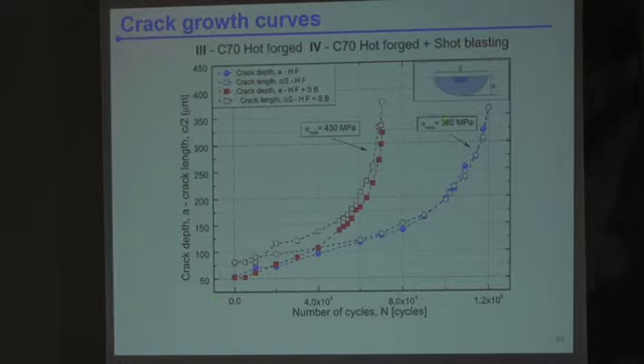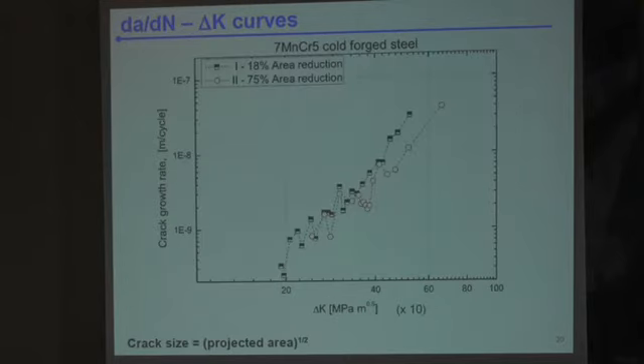It's, again, nearly the same thing for material number 3, where the two curves superimposed quite well, except maybe here at the beginning. But the main difference is for the red curve, where you do get a difference between the hollow symbols and the full symbols, telling you that indeed there is a difference in the crack aspect ratio for this material, which we don't have for the other.